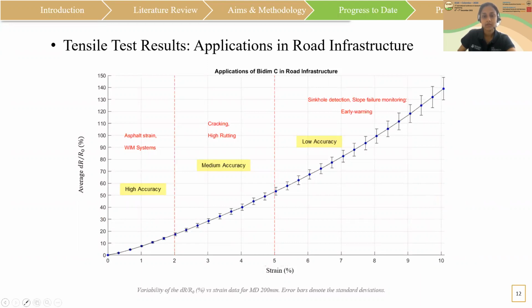So between 0 to 2% strain range, it can be used as a load sensor to measure strains in the asphalt layer and in weigh-in-motion systems. Similarly, from 2 to 5% strain range, where the accuracy is not as high, it can potentially be used to measure cracking or high rutting. For the strain range of 5 to 10%, it can be used in early warning systems for sinkhole detection and slope failure monitoring. Therefore, it can be seen that the applications are vast for this material in road infrastructure and the versatility is proved.